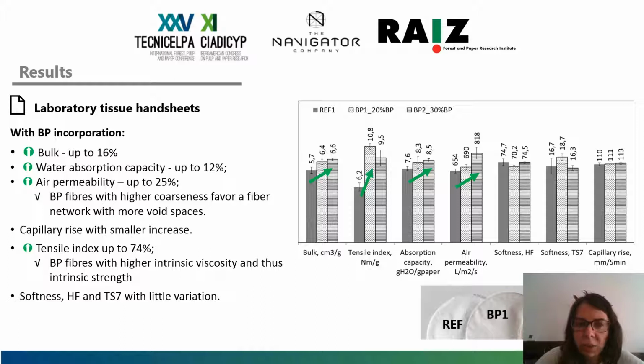And this result was attributed to the fact that we are incorporating fibers with higher coarseness in the furnish, so it results in a fiber network with more void spaces for water accommodation in case of water absorption and for air passage in case of the results of air permeability.